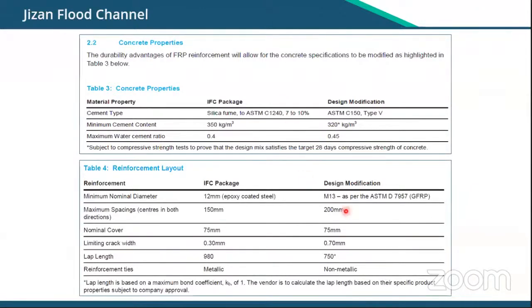I would say the biggest saving on the project was definitely that since the GFRP bar had a higher capacity, but also since the crack width requirement could be relaxed from 0.3 to 0.7. Why? Because there's no issue having a larger crack. There's no risk of corrosion of the GFRP bar, and therefore no risk of concrete bursting or spalling. This allowed increasing the spacing from 150 to 200. This is great because every time, instead of putting 4 bars in steel, now we only put 3 bars in GFRP.